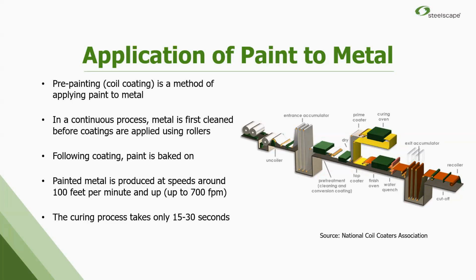15 to 30 seconds to cure and dry the paint. We have two coils we can load at the entrance. We have these accumulator towers, which move up and down and allow us to control how much product is in the line so that we can run continuously. There's a cleaning section. We clean the substrate and then we put a pre-treatment on it. And then almost everything gets a primer layer. That gets baked and cured. Then it gets its top coat or finish coat. That gets cured as well. Everything gets cooled down. At the exit of the line, we're wrapping that coil back up and off it goes to be formed into whatever final part it needs to be.